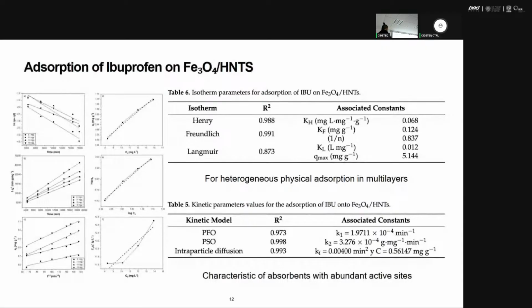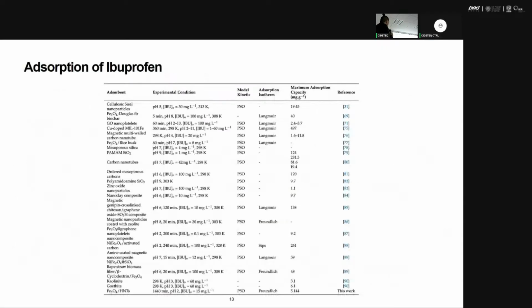And then I compare the result with another work. As I say, it was a really low quantity absorbed. It was around 5.1 milligrams per gram, compared with another material, the carbon nanotubes, which is around 81. But it is important to know the exact quantity of ibuprofen that is absorbed, which is mineralized.